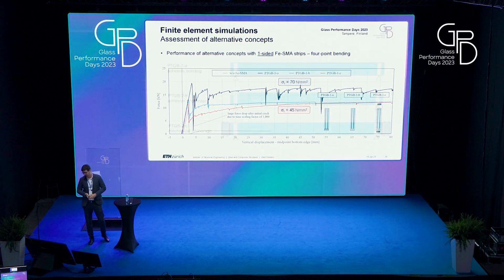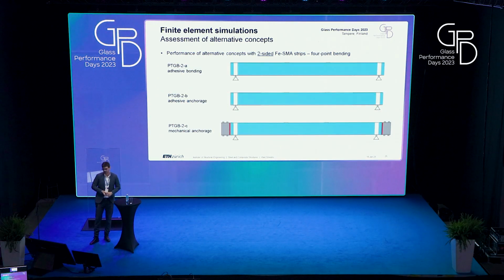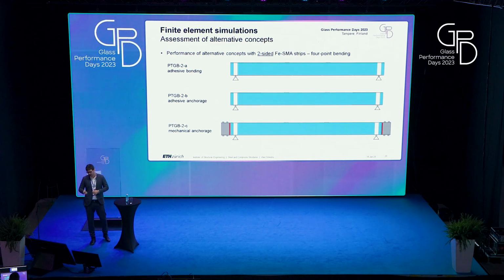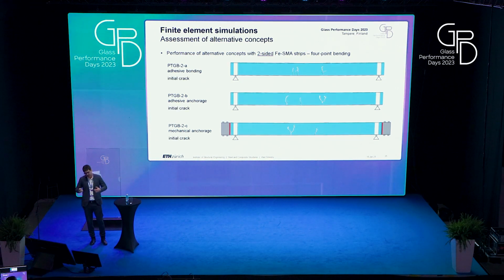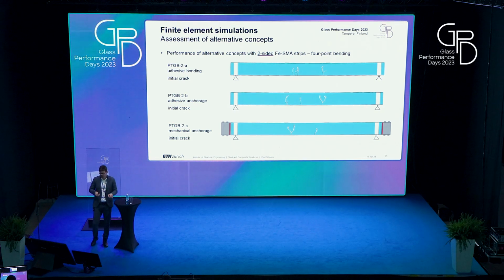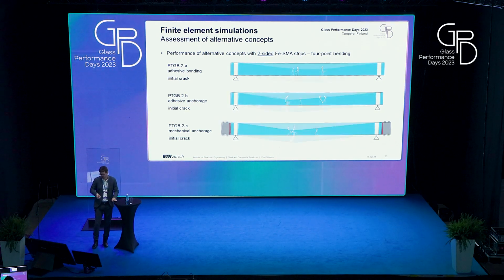And finally, I would like to also show you the cracking behavior for the concepts with two-sided strips that we observed for the different concepts. We can see the initial crack looks pretty similar. We have the 4-point bending load, and between our two loads we have the initial cracks.